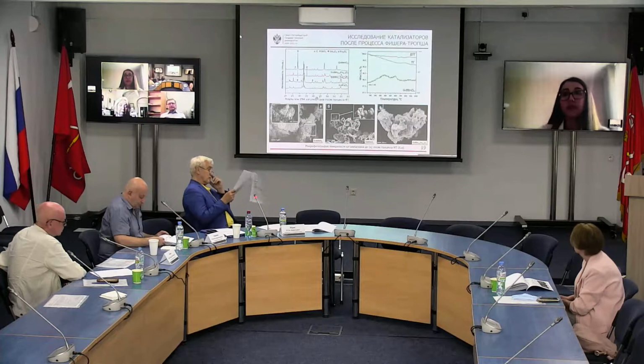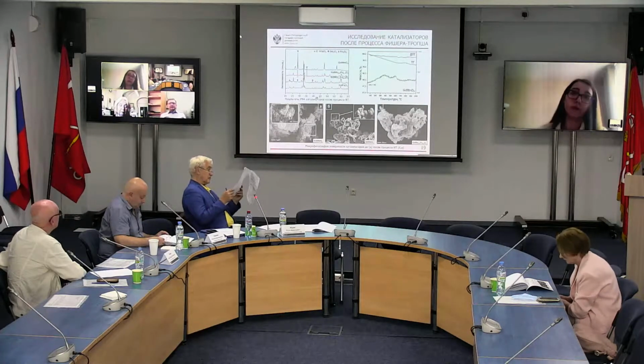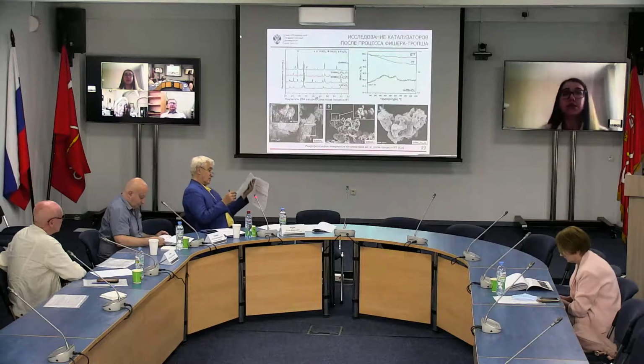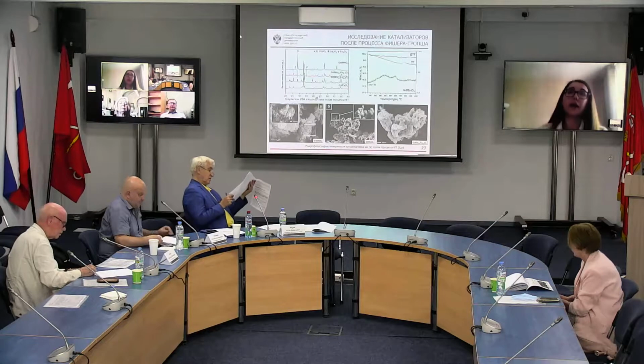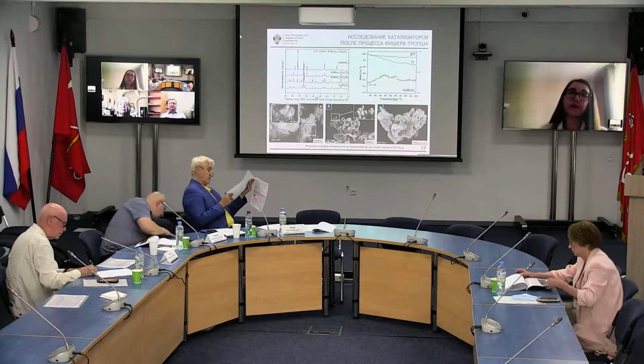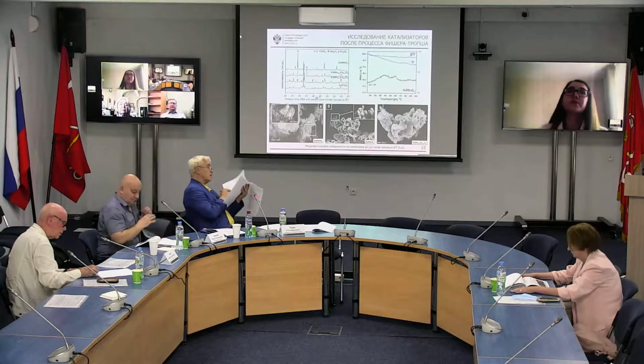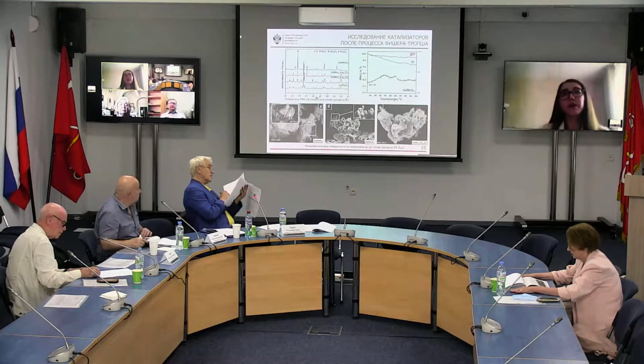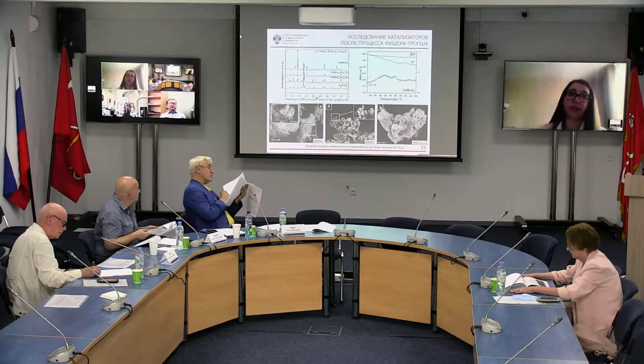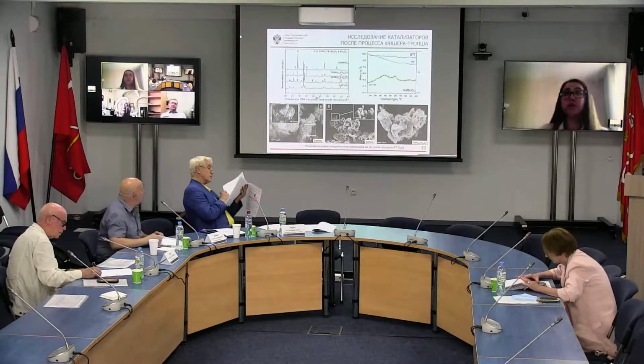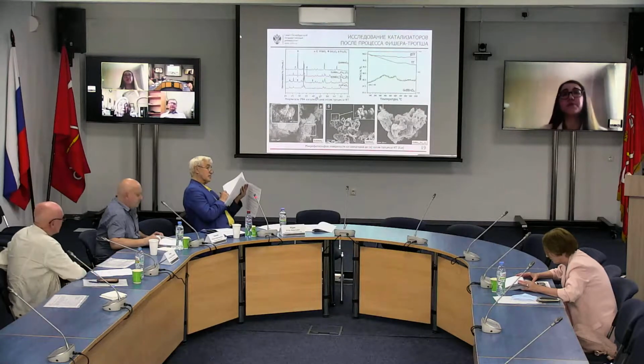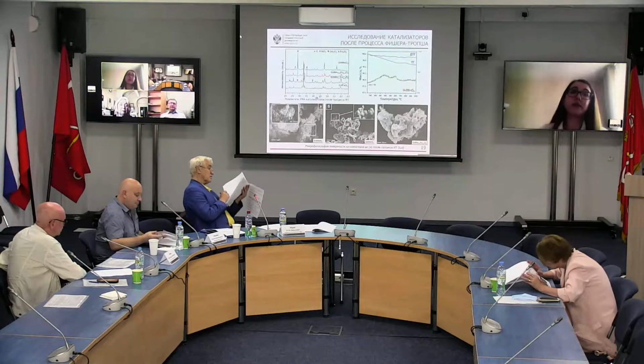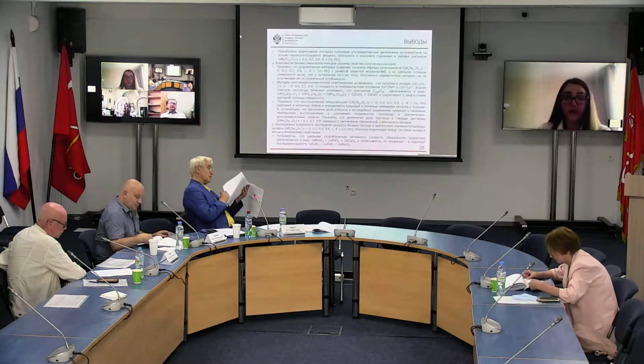Microphotographs of the surfaces of oxides after catalytic tests demonstrate the change of morphology, and we see the coking of the surface and aggregation of catalyst particles. Energy dispersive X-ray analysis showed that on the surface of catalysts after catalytic tests, we see carbon that is evenly distributed on the surface of the studied catalysts. And here on the slide, just as an example, you see the curves of thermogravimetric analysis of gadolinium manganite that demonstrate insignificant loss of mass, roughly 0.5%. And this demonstrates a low level of carbonization of the surface. Similar results are observed for all the studied substances of this series.